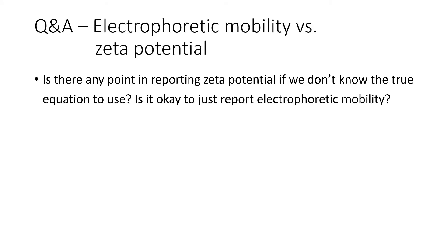You'll reach the same conclusions and avoid having to contend with all the assumptions and caveats this webinar has been concerned with. I haven't discussed non-polar dispersions at all, which was the primary purpose for developing POWs, but the concept of zeta potential in non-polar media is questionable, at least. Given one or two elemental charges, how can you define a double layer? What or where is zeta? So quite honestly, most of the time, I stick with mobility.